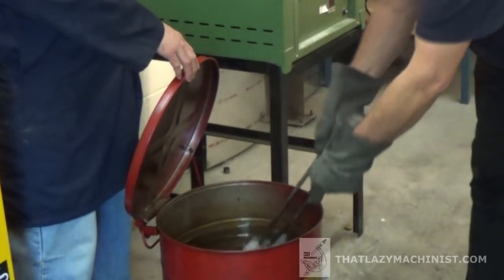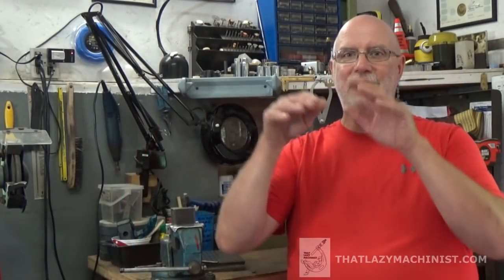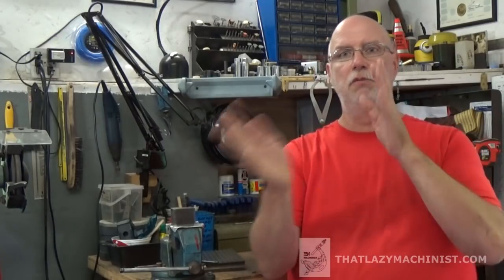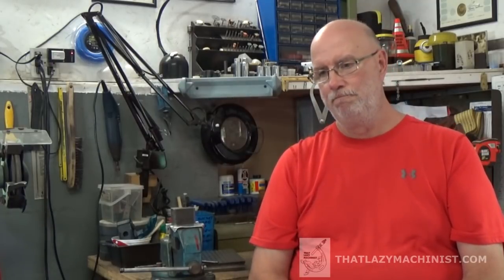When I dunk a part in oil, I want to keep it dunked. Now, heat treatment oil has a flash point of somewhere around 600, 650 degrees. I forget, somewhere around there. And that means that it will spontaneously ignite at that temperature. Great. As long as I keep that temperature below that, it won't ignite. My part, let's go back to our 4140, needs to be around 1550 degrees before I dunk it in the oil. That means I'm going to get a fire.